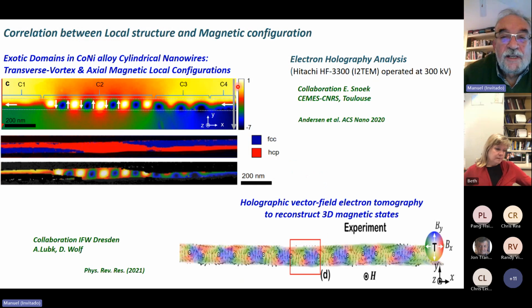And for example, in collaboration with people in France, through the electron holography analysis, we were able to obtain also what we call exotic domains in cobalt nickel alloys, where you see locally, in this red region, we have a hexagonal crystalline structure with vortex and transverse domains perpendicular to the axis of the wire. While as we move to the right, we have this blue region where the crystal is cubic, and we have finally axial magnetization. And this has been obtained also experimentally in collaboration with a group in Dresden through holographic vector field electron tomography.